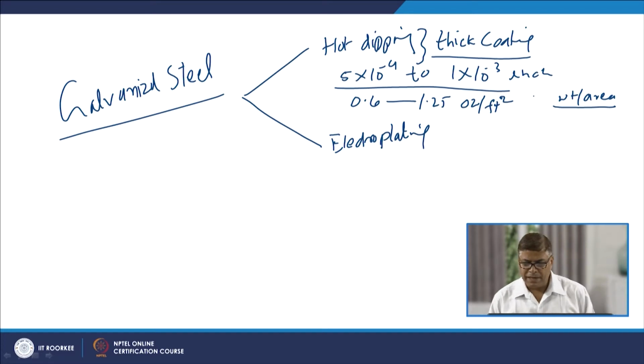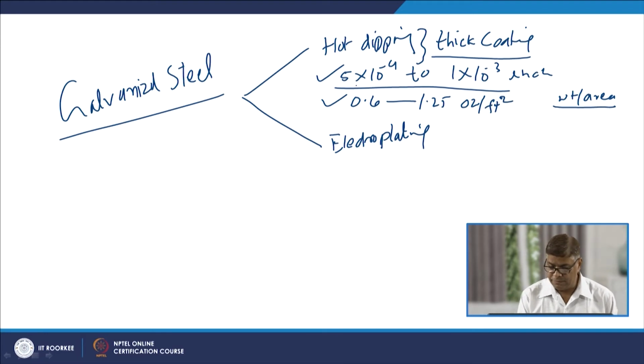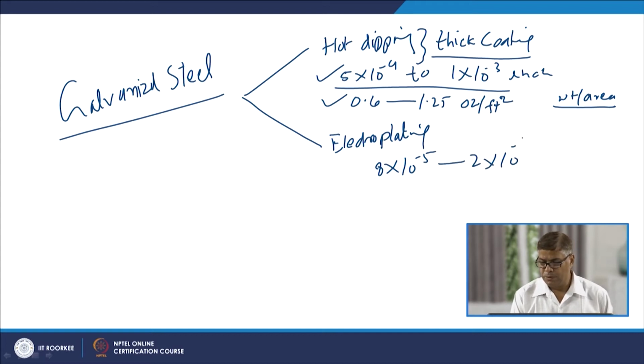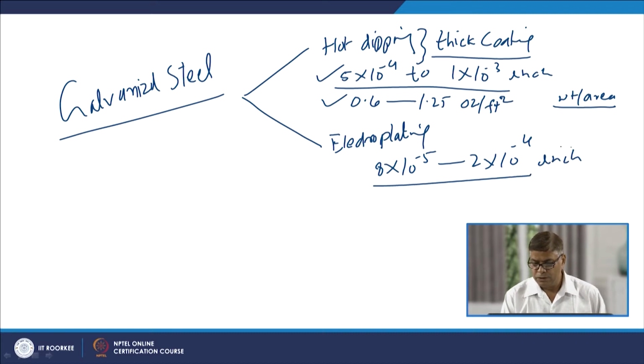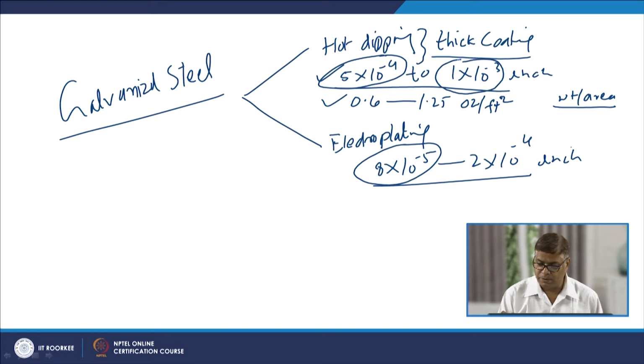These values of the thickness as well as the zinc per unit area in case of the hot dipped coating are much more than those available with the electroplated coatings. In case of electroplating, thickness varies from a very low level like 8 x 10^-5 to 2 x 10^-4 inch. So, if we compare, here the minimum thickness is 5 x 10^-4, and here the minimum thickness is 8 x 10^-5, and the maximum thickness is 1 x 10^-3, and here the maximum thickness is 2 x 10^-4. So, there is a lot of difference in terms of the thickness.